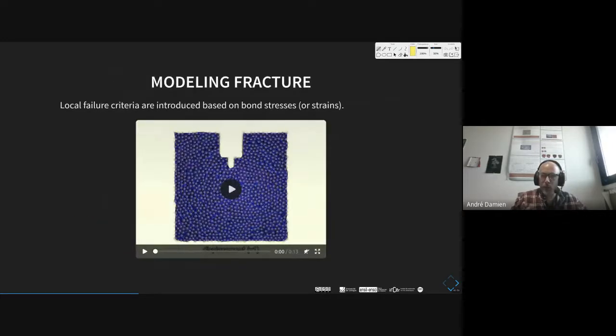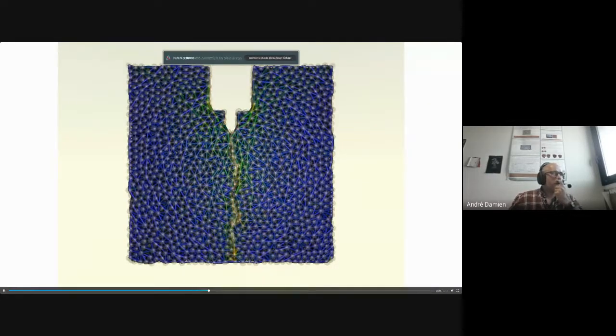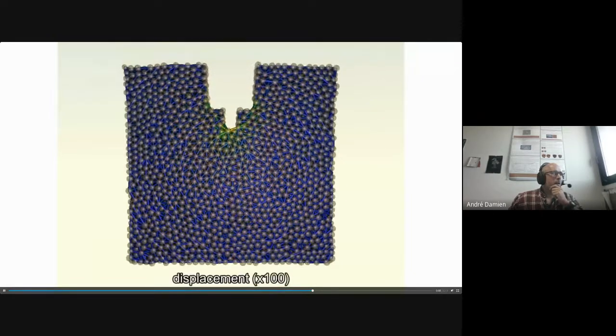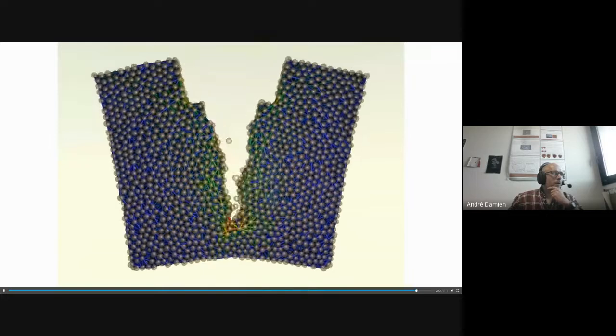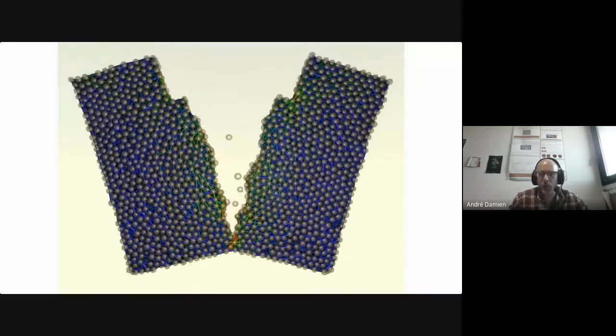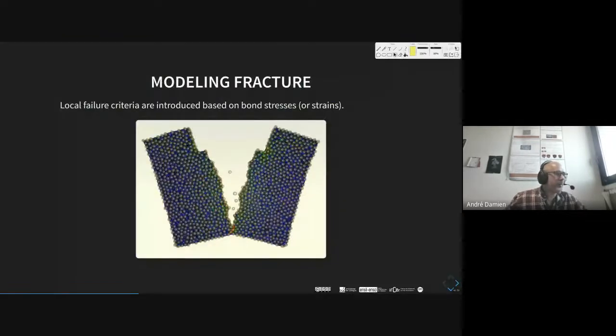So the main interest, in fact, is to introduce local fracture criteria inside these bonds. And this is what we do in this video. Here you can see the propagation of fracture, and here the displacements are magnified. As you can see, we can obtain the initiation and the propagation of fracture. These failure criteria are quite simple. Generally, they are based on local stresses or, less generally, on strains.